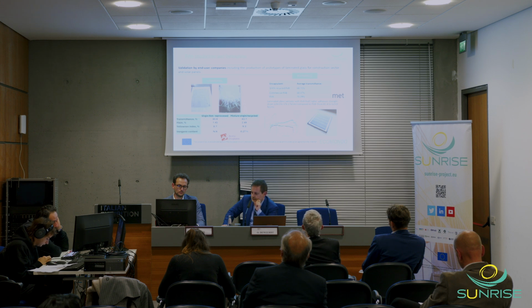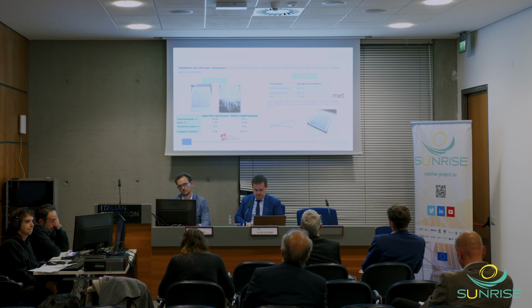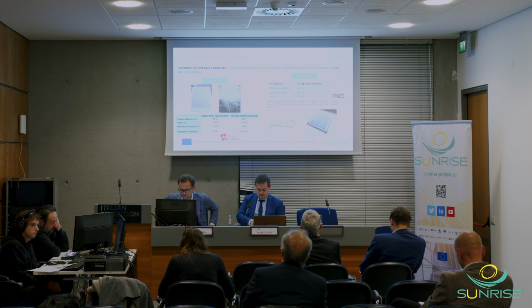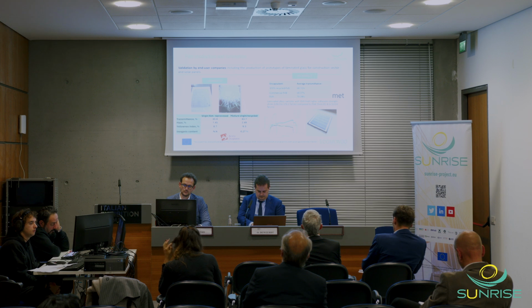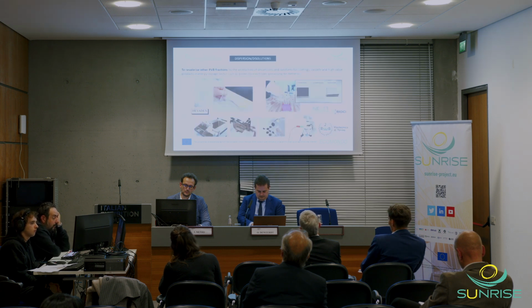In the case of PV panels, what we have is values comparing EVA, which is the currently used encapsulant, with commercial PVB and with recycled PVB. Here we see that in terms of transmittance, there is not so much difference regarding EVA. So in terms of transmittance, PVB could work. In the case of adhesion, we have had some problems, but again, we have to see if these problems are due to lack of homogeneity in the processing of the film, or if it is really due to the characteristics of the PVB. Okay, this was the main application.